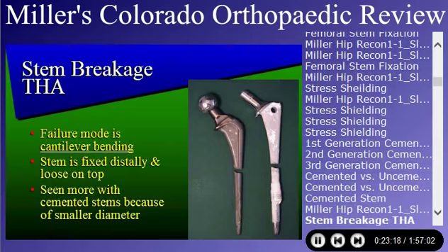Stem breakage, remember for the test question, the failure mode is cantilever bending, and it doesn't matter whether it's a cemented stem like you see on the left or a non-cemented stem, which is seen on the right. Basically, the stem is fixed distally and loose on top, and it starts to cantilever bend around the midshaft. It's seen more with cemented stems because they tend to be of smaller diameter. But you can use a small diameter non-cemented stem and get the same cantilever bending, and it'll break. Just remember the mechanism is cantilever bending.